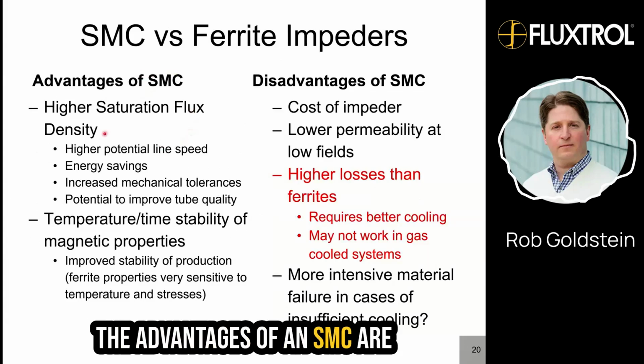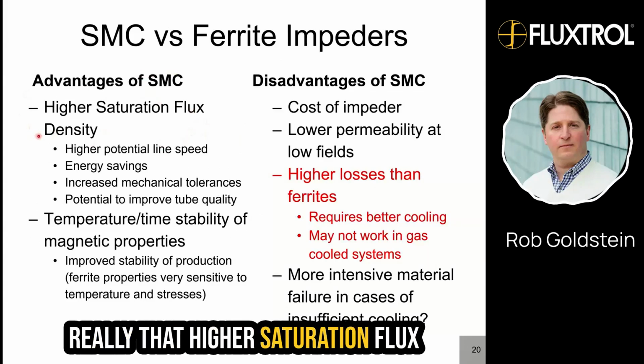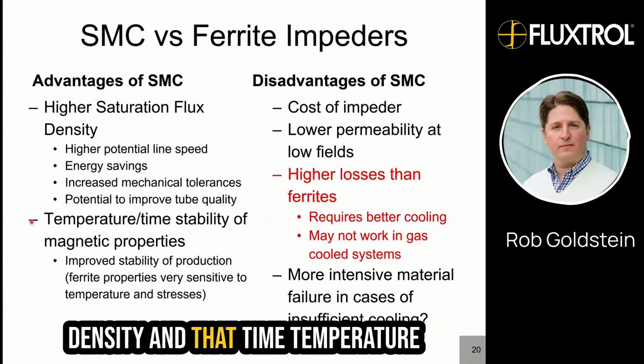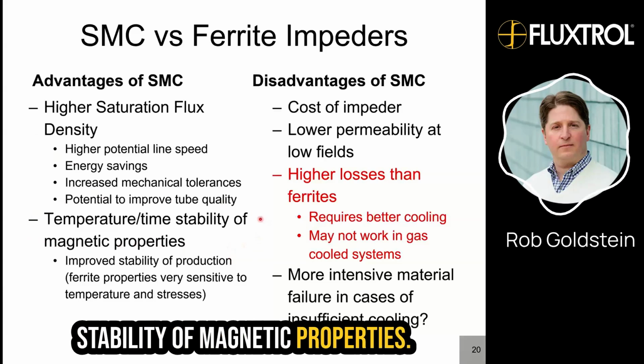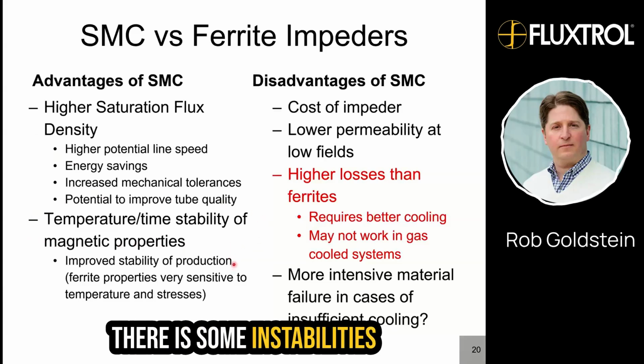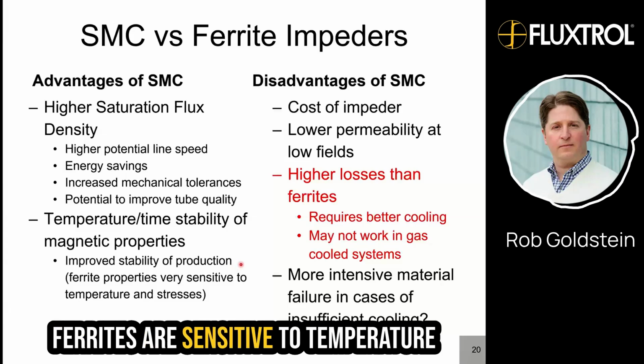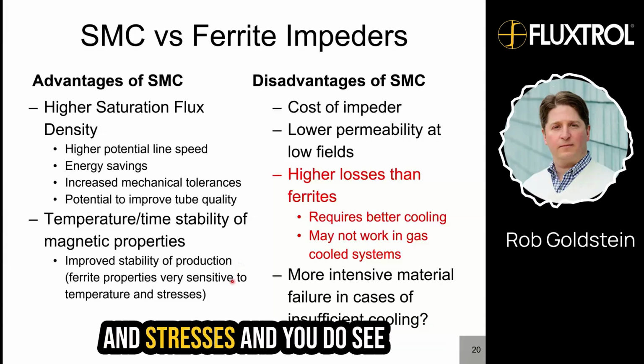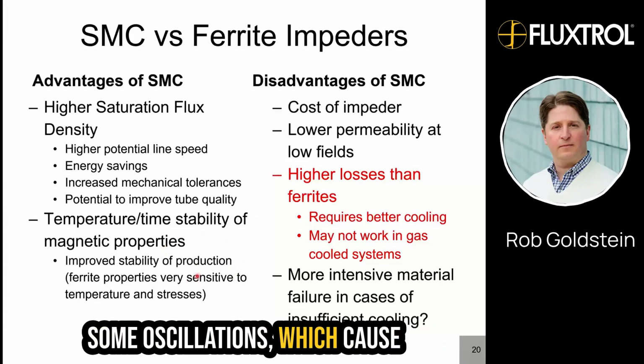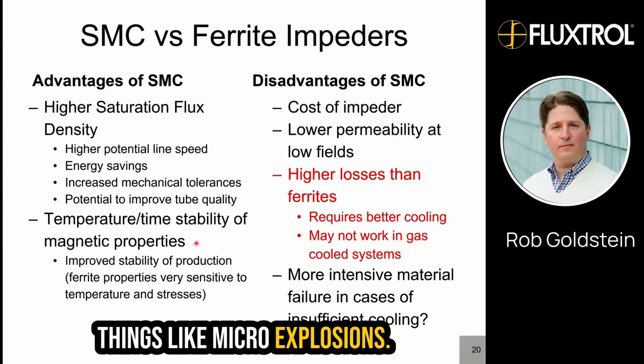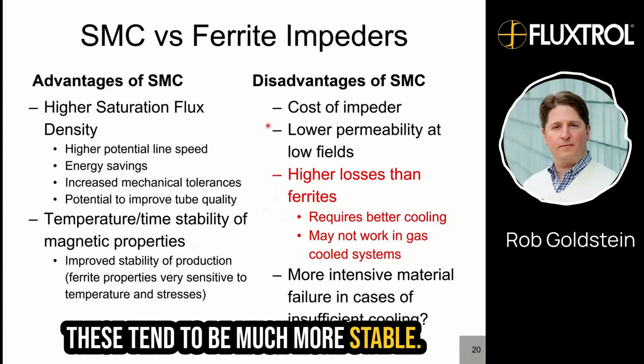The advantages of an SMC are really that higher saturation flux density and that time-temperature stability of magnetic properties. There are some instabilities in production. Ferrites are sensitive to temperature and stresses, and you do see some oscillations which cause things like micro explosions. These tend to be much more stable, the cores.